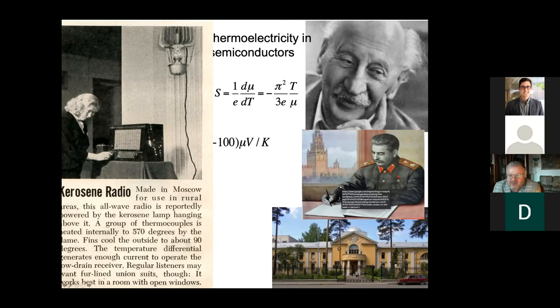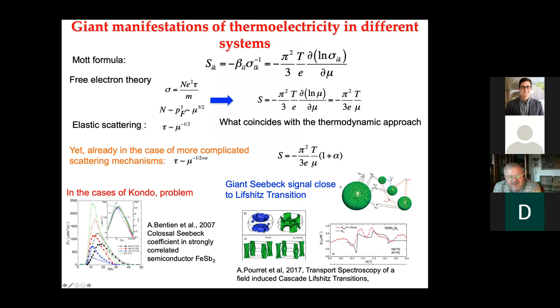In this laboratory many interesting discoveries were done, theoretical and practical, in the field of thermoelectricity. Okay, I will proceed. Then in physics, when can the Seebeck coefficient become giant and why is it important for fundamental research? Because there exists the Mott formula, which is more general than the Kelvin one. It says that the Seebeck coefficient is proportional to the derivative of the logarithm of sigma over the chemical potential. And you understand that sigma also contains information about scattering processes. So every time you have some singularity, a strong dependence on chemical potential, or a strong dependence on the energy of scattering, the Seebeck coefficient can increase.